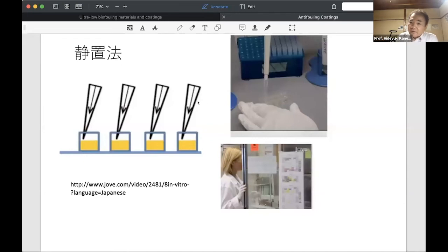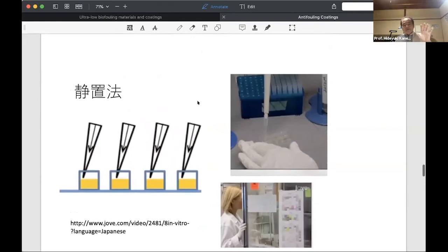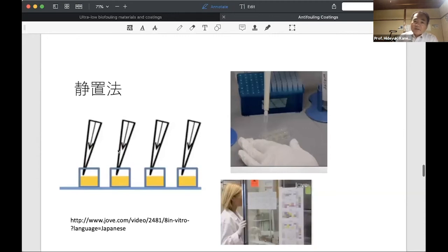This is one of the methods. Sorry, this is another method. I have shown you the flow type laboratory biofilm reactor, but in this case, another static method: plastic wells. I show you right now. Specimens and the bacteria culture are put into the well, and each well is filled with the bacterial solution. Then they are put in the incubator for a couple of days or a couple of hours. After the incubation, we remove the specimen and then we analyze the biofilm on the material surface.